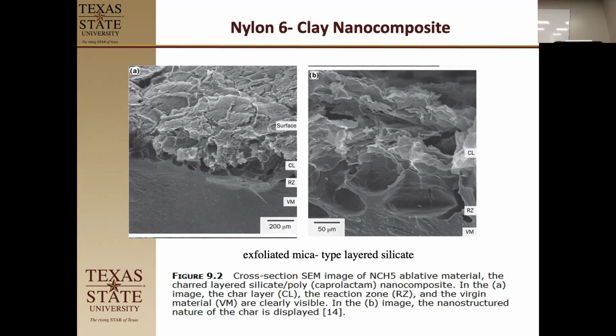This particular one is using a direct force. So they have a rocket motor shooting directly at it, and it's orthogonal. So we don't see the flow in this particular picture, but toward the edges, you can actually see streaming. And I'll show you a couple of pictures of that. If you blow up the layer, here again, this is the char zone with the large holes, the large barriers that help keep it thermally insulated. And then the reaction zone is starting to expand a little bit, and the virgin material looks like a nice piece of nylon.